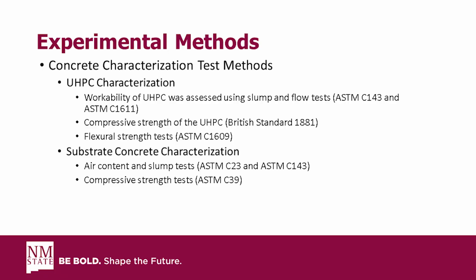For our substrate characterization, we just provided air content and a slump test, run in accordance with ASTM C231 for the air content and ASTM C143 for the slump. And then we did do compressive strength testing, run in accordance with ASTM C39.